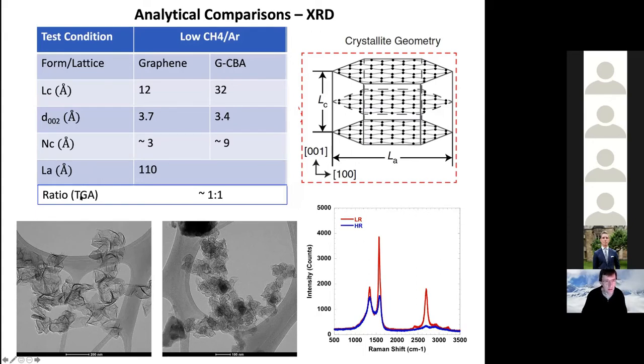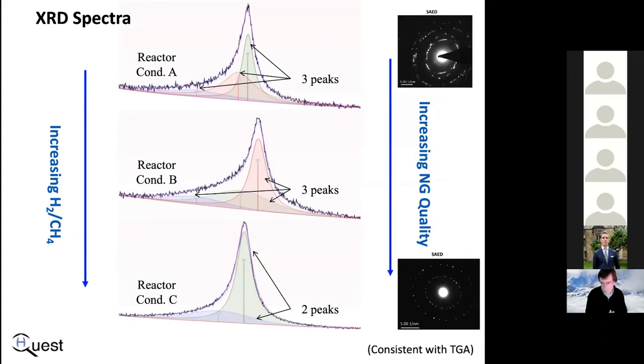But again, roughly based on the TGA derivative spectra, assigning fractional content to the mixed product form, the two forms, graphene and the carbon black analog, occur roughly in a 1-to-1 ratio. The TEM images for your reference are shown below. The crystallite geometry is again shown in the upper right, as well as the difference between low ratio and high ratio methane to argon for the two cases, red versus blue, illustrating the capability to tune, if you will, and/or select which product by reactive condition.